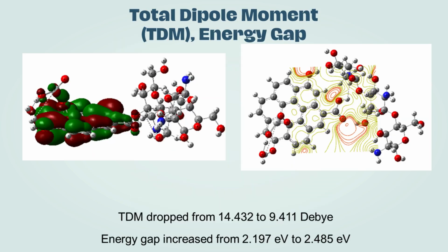This is the first interaction, with the H2O molecule. The total dipole moment and energy gap changed upon interaction, signifying successful sensing. The molecular electrostatic potential contours indicate the composite is still reactive for further interaction.